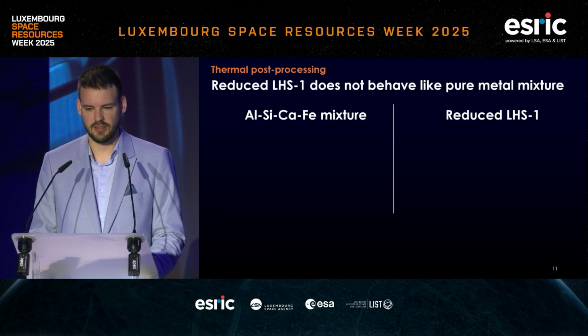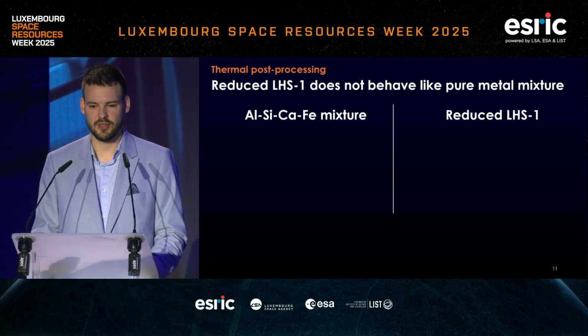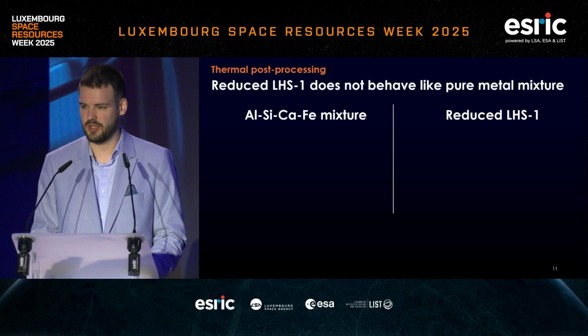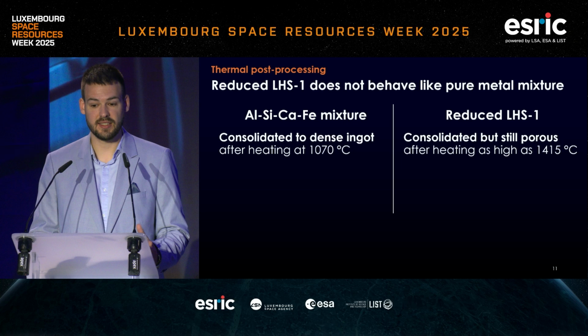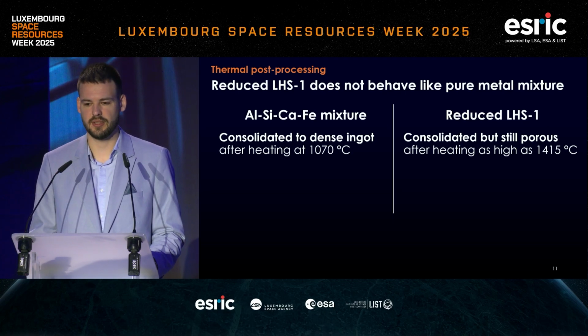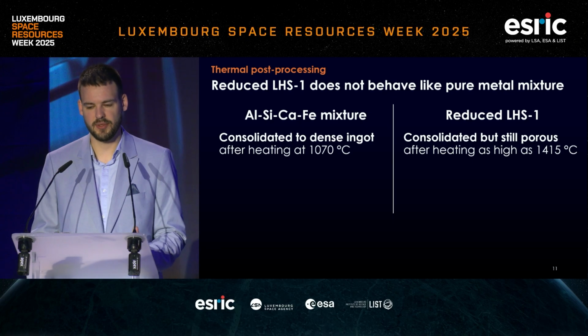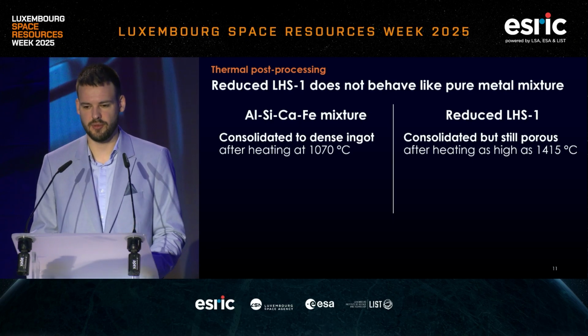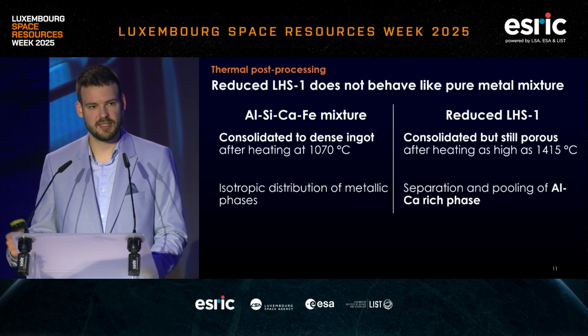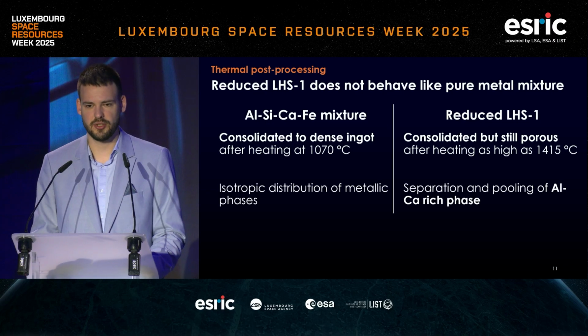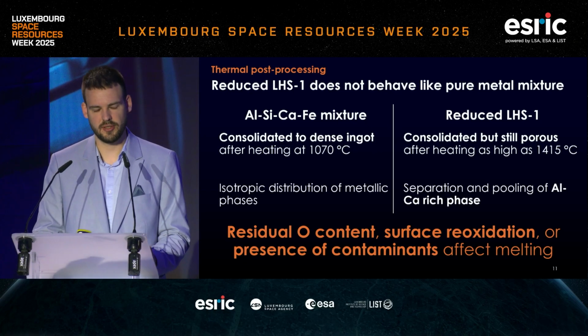So to summarize this part of the work, on the left we have the results with a kind of idealized mixture of aluminium, silicon, calcium, and iron, and on the right what we actually observed with reduced LHS1. We can see on one side we get, as expected, a nice melting and ingot formation, slightly above 1,000 degrees C, whereas with actual products from the FFC process, the consolidation happens, but not fully, and we don't have a nice melt pool formation, even as high as 1,400 degrees. We also observe a phase separation that we do not expect from the idealized mixture, where the phase distribution is isotropic.